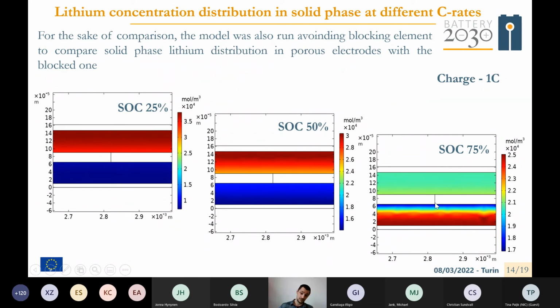...a distribution of a gradient also of concentration of lithium in the solid particle inside the anode from the surface to the bulk. This behavior could also be evident in the previous panel with the blocking elements, but the problem is the scale of the plot. You can notice the gradient here because the scale is different, but with the interfering elements, they induce an abnormal pattern in lithium distribution, flattening the gradients that you can observe here.